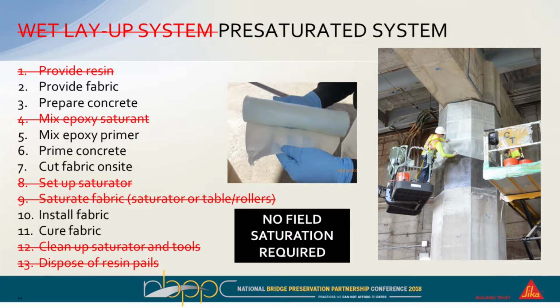So again, if we compare that to a pre-saturated system, what it allows us to do is cut out about half of the installation steps. The biggest time saver is really the mixing of the epoxy resin and the actual saturation of the fibers. That's the part that probably consumes at least half of the installation time, even before you bring it out onto the column and actually start wrapping it.